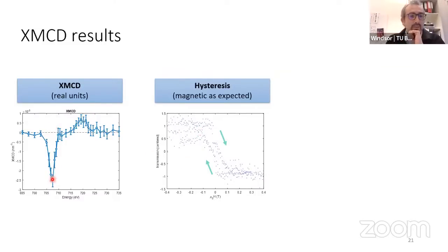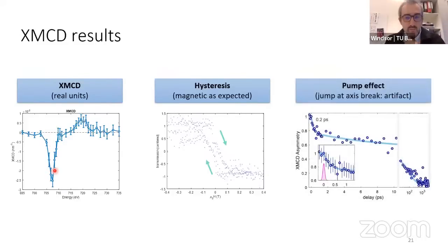And now we stay at this energy, and we're still probing this magnetic contrast, and we shoot the system with our laser. And this is what we get. So this is now another curve showing us dynamics from FGT. This inset here is just a close up because I wanted to make sure that I present the error bars, because the error bars are not so small. And also the time resolution. So the time resolution here is actually very good. It's 100 femtoseconds or so.